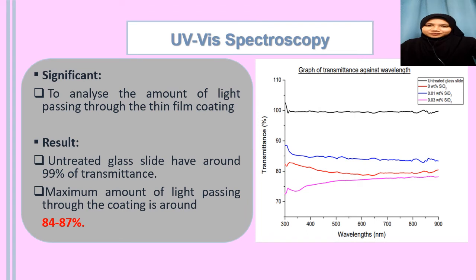Okay, the thin film coating is characterized by using UV spectroscopy. The significance of UV is to analyze the amount of light passing through the thin film coating. From the result, we can see that the untreated glass slide has around 99% of transmittance. However, the maximum of light passing through the treated glass slide is around 84 to 87%. However, it achieved the expected result, which is that the light transmitted should be more than 80%.